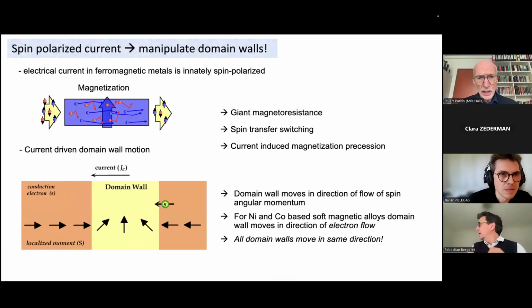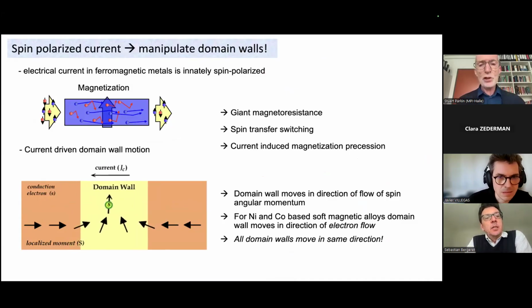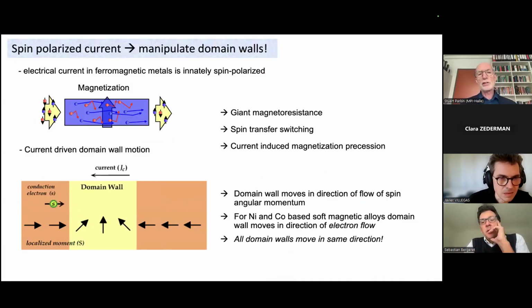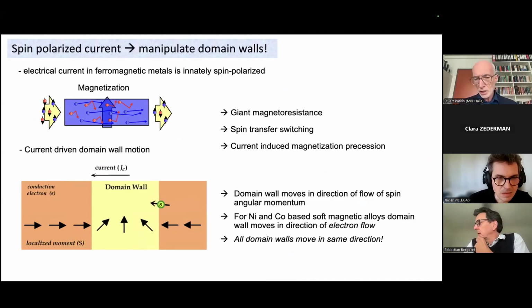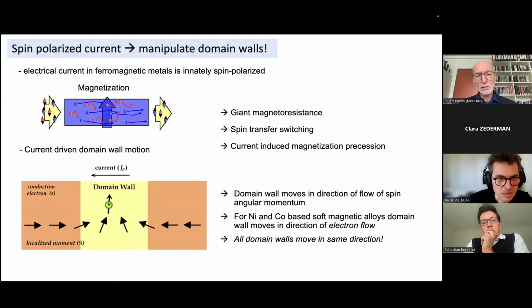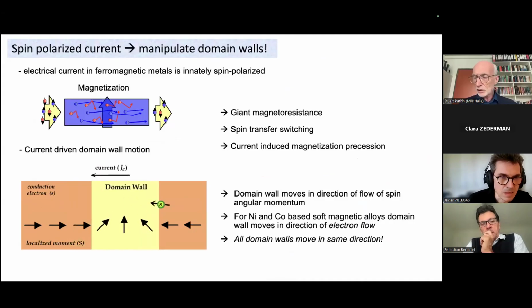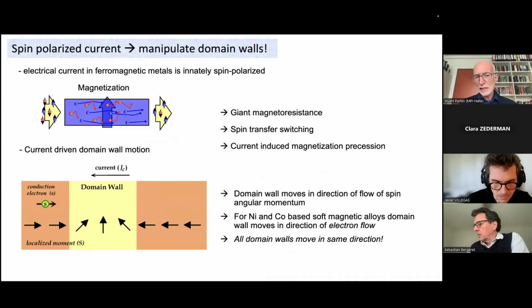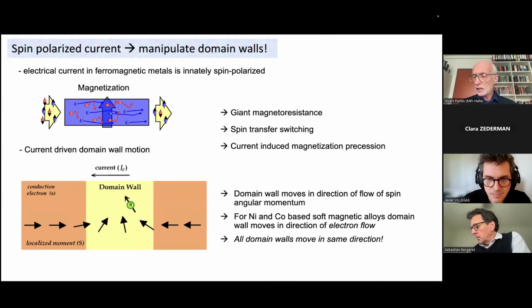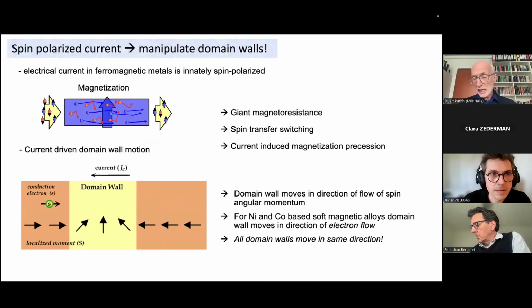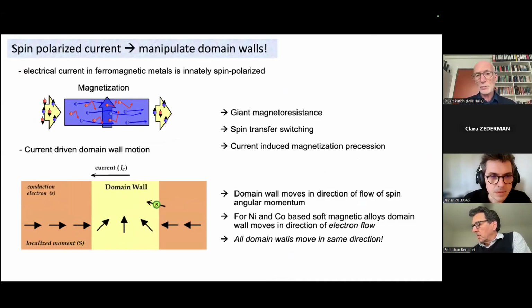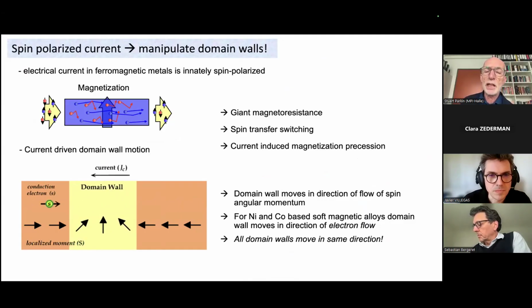So I want to briefly then introduce racetrack memory. This was a concept that I proposed in 2002, and the very simple concept is this, that if you introduce current into a magnetic material shown at the top, then the magnetic material will scatter electrons of one spin orientation more than the other spin orientation. And this actually was known about even in the 1930s due to Neville Mott. And the current then becomes automatically spin polarized through this spin-dependent scattering within the bulk of the magnetic material.